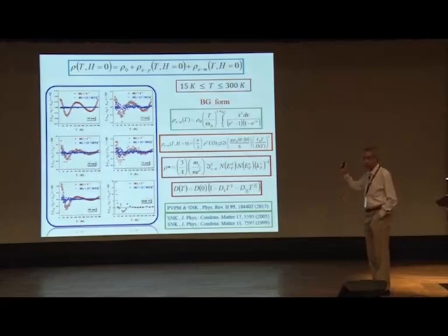Now, once we bring in the renormalization of spin wave stiffness into it, you see that not only are the deviations reduced by an order of magnitude, but they are now statistically distributed around 0. That means you now have the right functional form, which describes your observed data properly, and we can actually estimate accurately their different contributions.